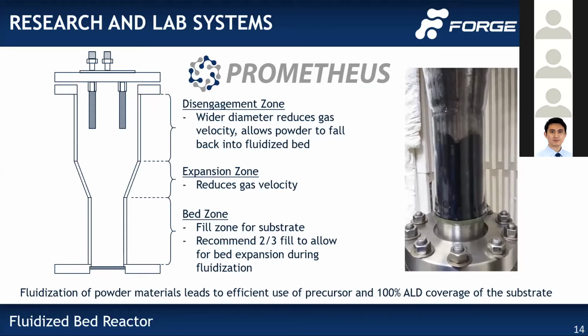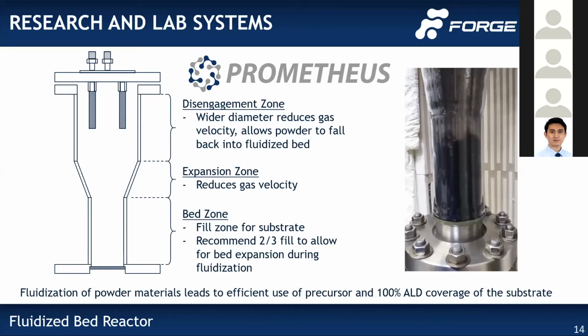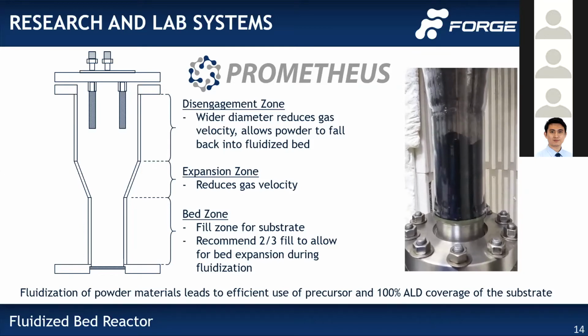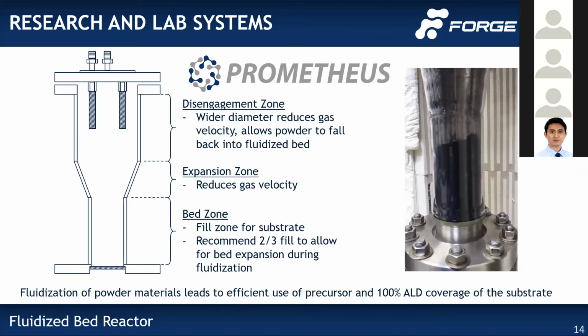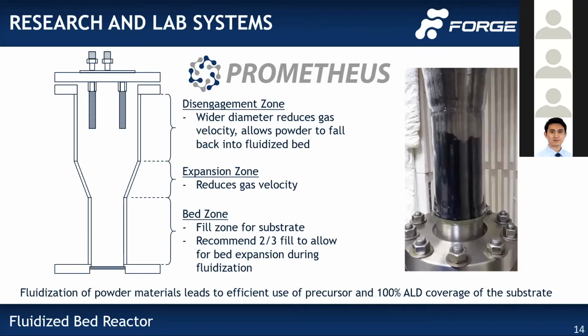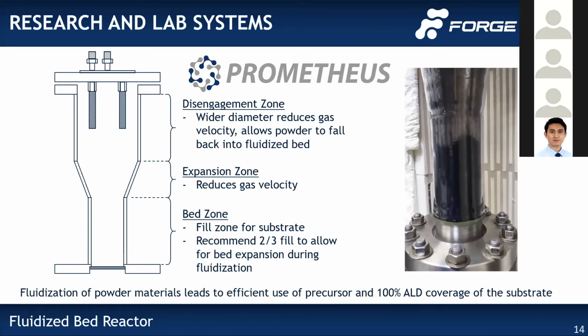You have the bed zone or fill zone where you put particles, powder into the reactor. That expansion zone is where you're reducing the gas velocity so your particles actually drop back down and stay within the reactor, including that disengagement zone so your particles will stay down within the reactor zone.